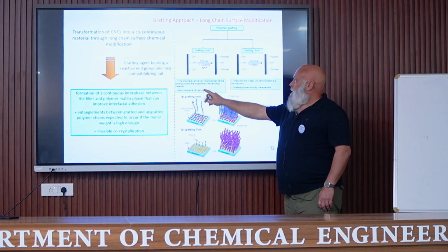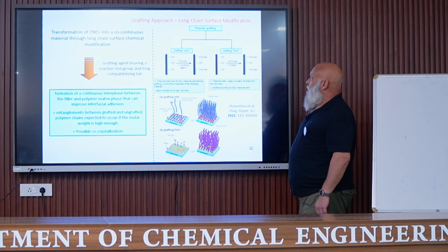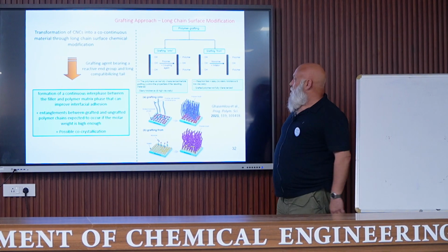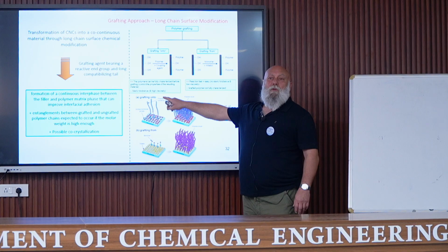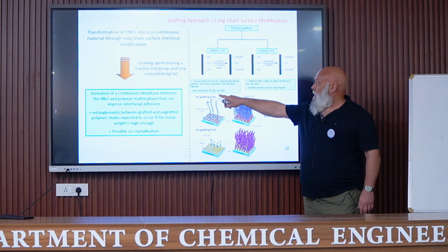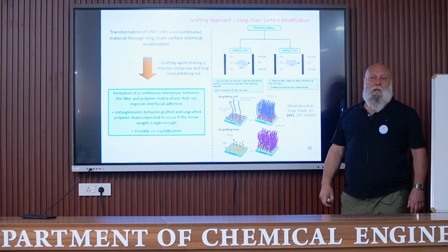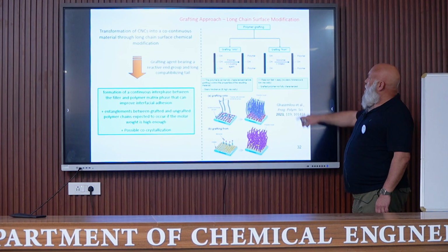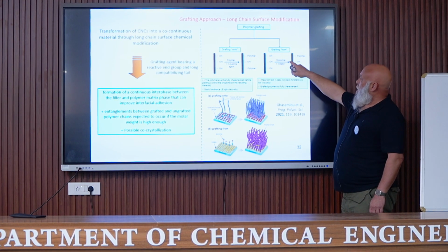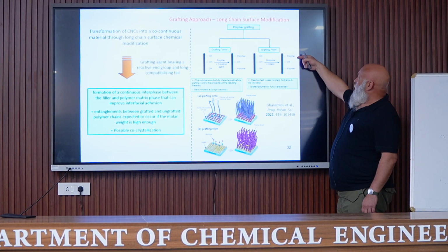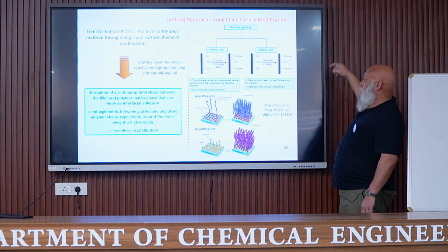The good thing is that the polymer can be fully characterized before grafting. We know the molecular weight of the polymer, but of course the viscosity of the medium is higher because of the polymer, and there are some problems of steric hindrance. The other strategy, grafting from, consists in mixing the nanoparticle with a monomer and an initiator, and the polymer grows from the surface.